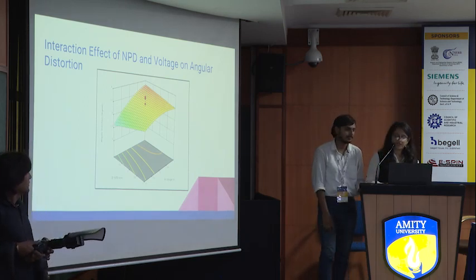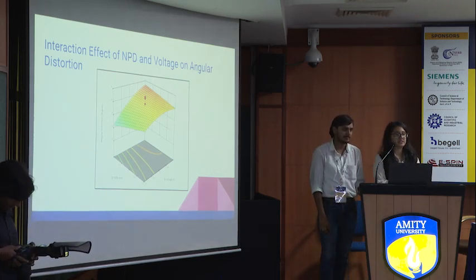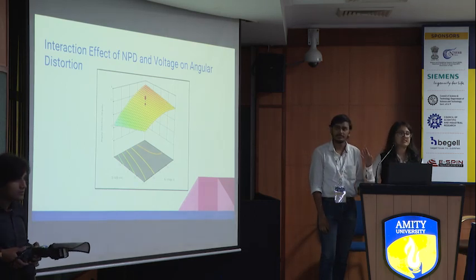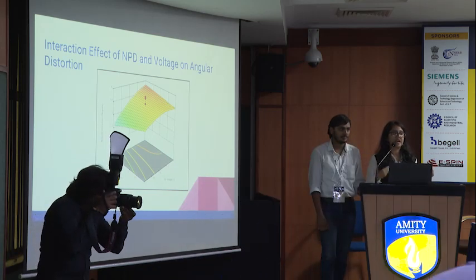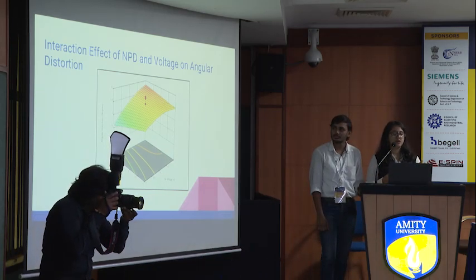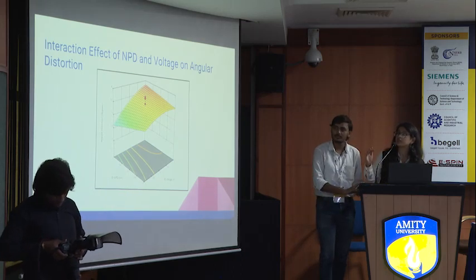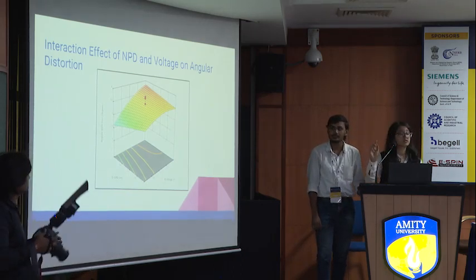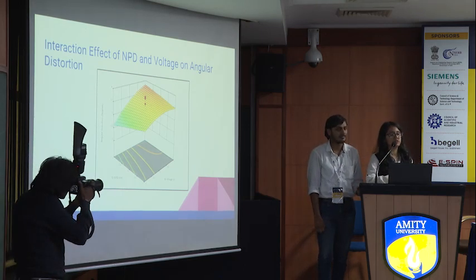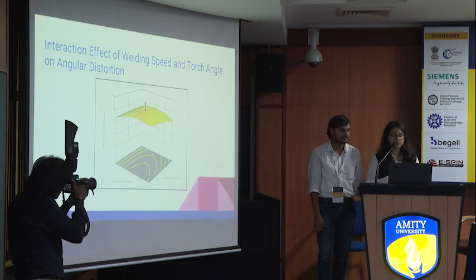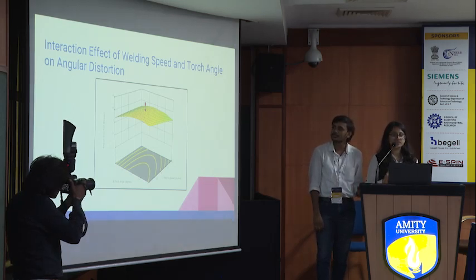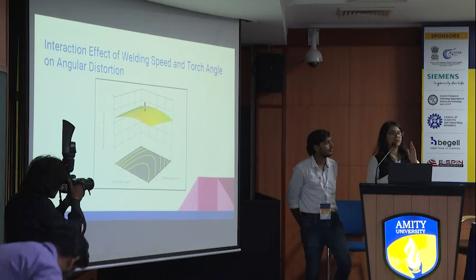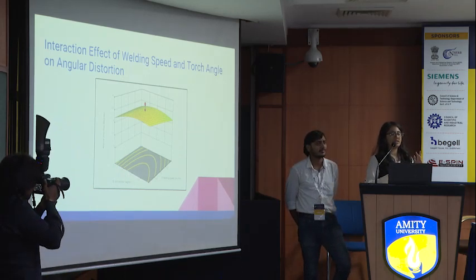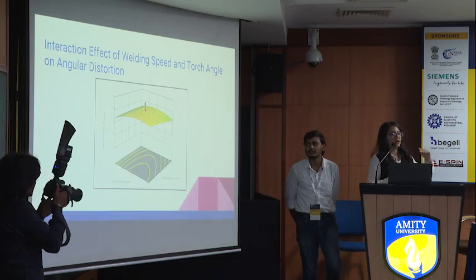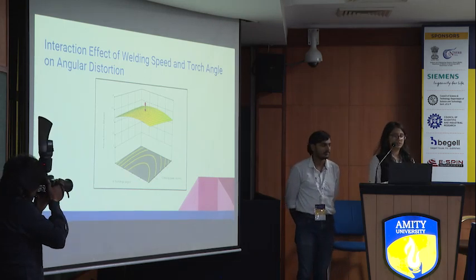Okay, so as we have seen in the previous graphs, for nozzle to plate distance and voltage, here we are seeing the combined effects when we consider nozzle to plate distance and voltage all together. So what would be the effect on angular distortion? As you increase the voltage and increase the nozzle to plate distance both simultaneously, the angular distortion would also increase. Coming to the next, torch angle and welding speed. In this, if we decrease the welding speed and increase the torch angle till a certain point, the angular distortion will increase, and after that, even if we increase the welding speed and increase the torch angle, the angular distortion will fall.